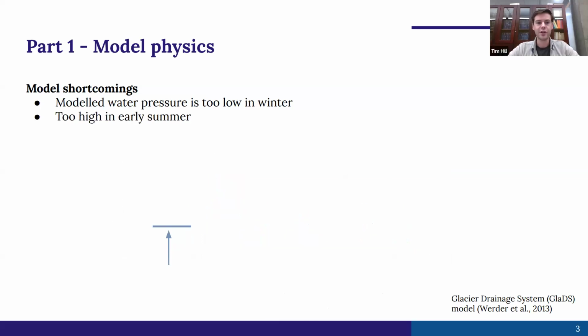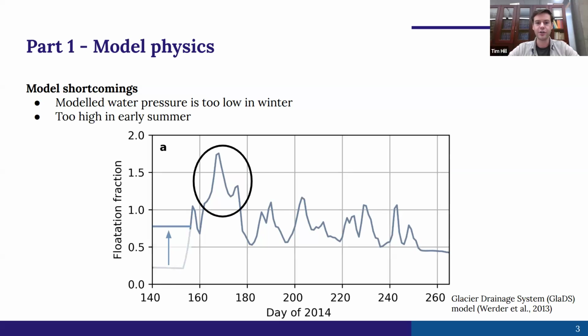The other thing I see with this curve is that my water pressures are very high when surface melt first really reaches the bed in this pulse here. Water pressures are above 150% of overburden, and this lasts for 20 or 30 days. That's a little bit non-physical because, of course, you'd have some uplift of the ice, which increases drainage capacity and lets that water be drained.